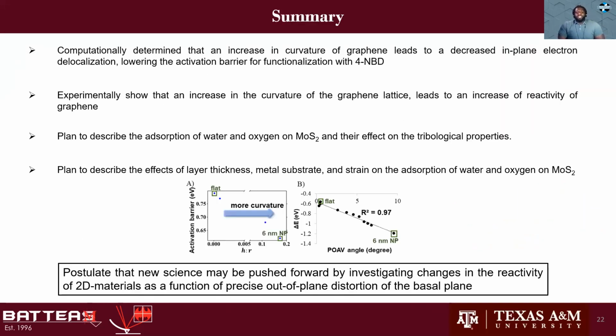And so just to reiterate, experimentally and computationally, we determined that controlled out-of-plane strain can be applied to graphene, and we see that with increasing curvature, this disrupts the in-plane delocalization of graphene, yielding a decrease in the activation barrier of our test reactions as a function of increasing curvature. And we are continuing to work on describing the absorption of water and oxygen on MoS2 and their effects on tribological properties. And we postulate that new science may be pushed forward by investigating changes in reactivity of 2D materials as a function of precise out-of-plane distortion using mechanical force to the basal plane.